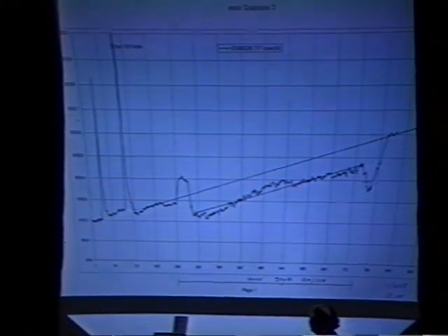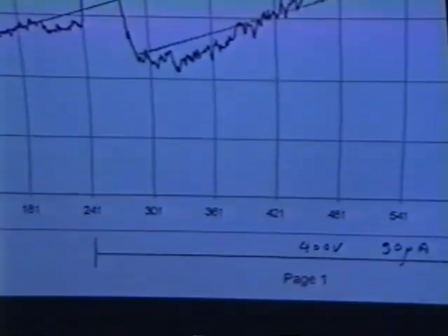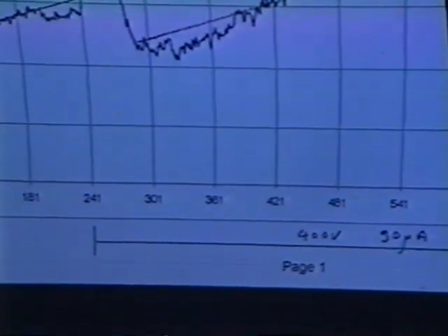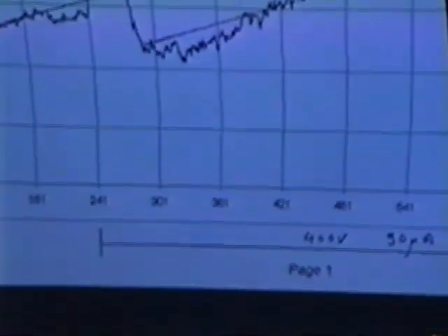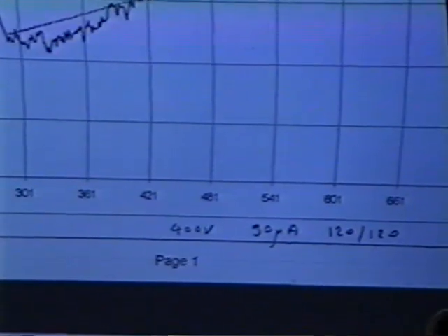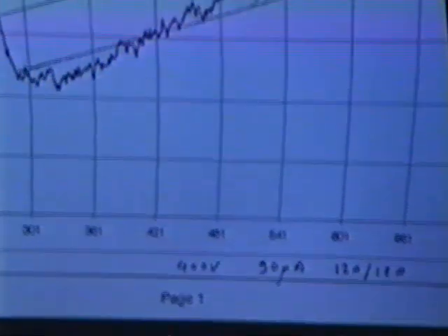So forget about glitches here, they're just the computer fade. At the same temperature, now we put DC voltage. In that case, 400 volts, 90 microamps. And now you see first an increase in temperature due to the Joule heating. So that means the system is responding correctly. When we put in heat, the temperature rises. So that's correct. And then it went down, stayed down, until you turn it off.